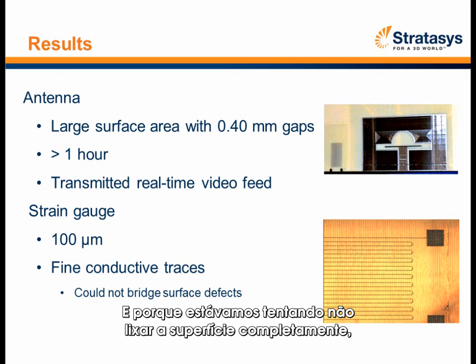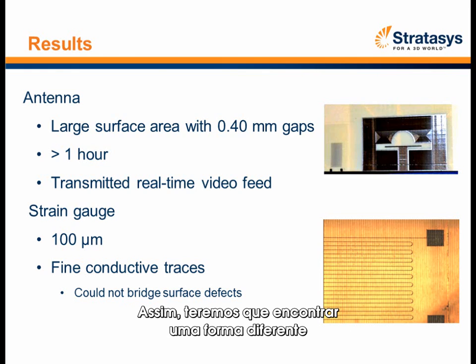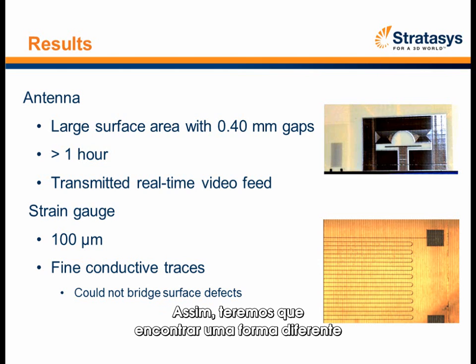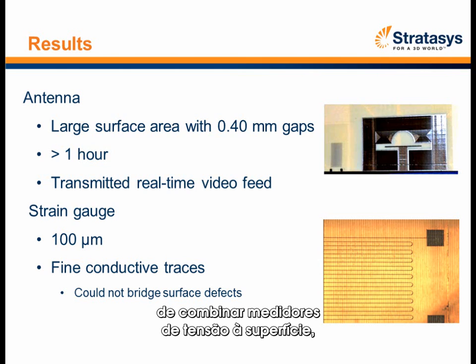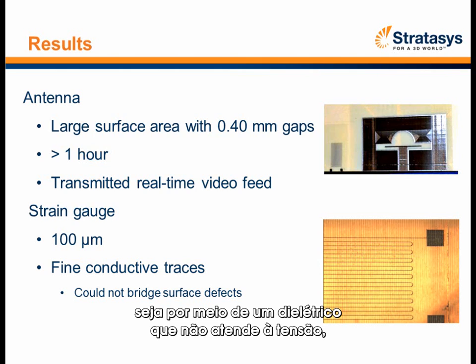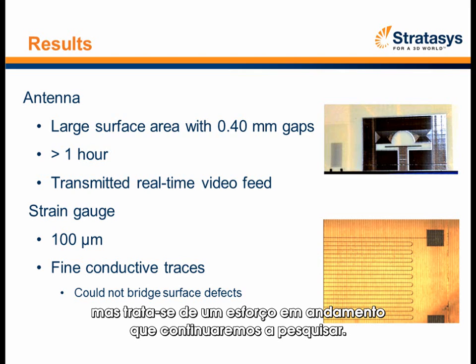And because we were attempting not to sand the surface completely smooth, we were trying to work with the as-fabricated surface minus just the grit blasting. And we found that we couldn't get the traces to be consistently conductive without localized errors. So we'll have to find a different way to marry strain gauges to the surface, whether that's through a dielectric that doesn't mask the strain, but that's an ongoing effort that we need to work on.